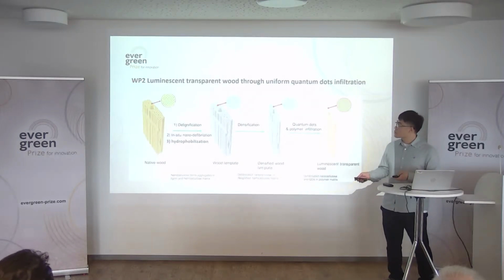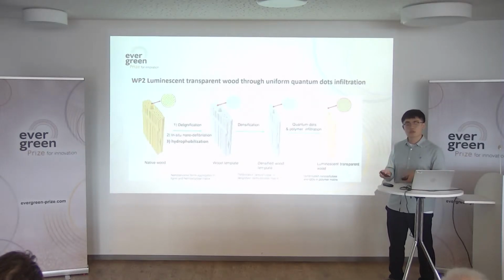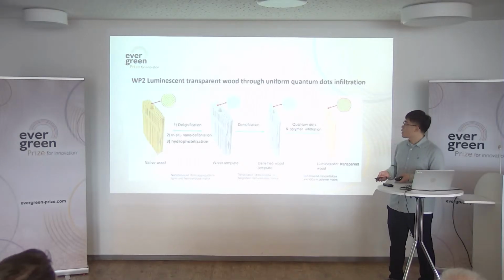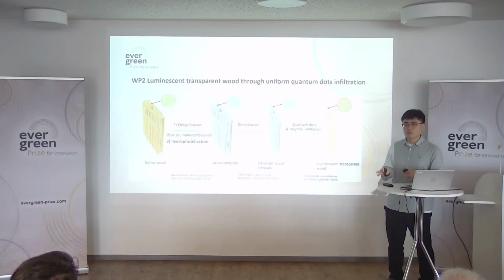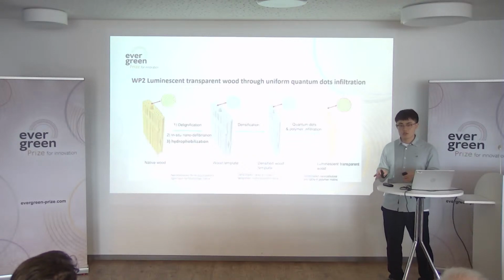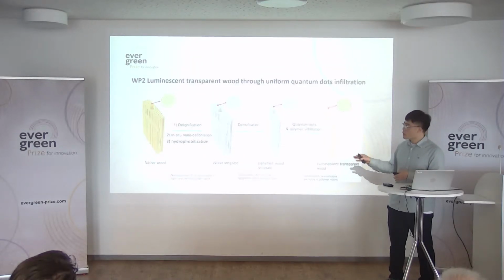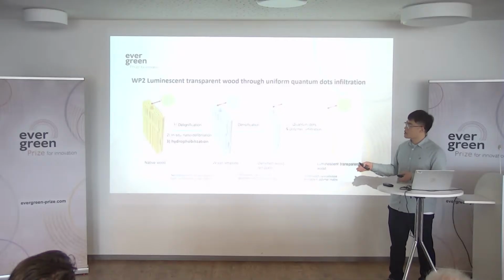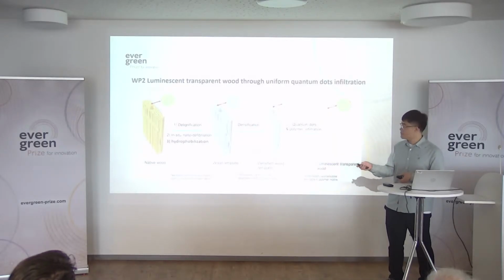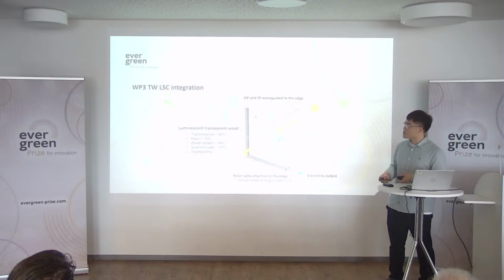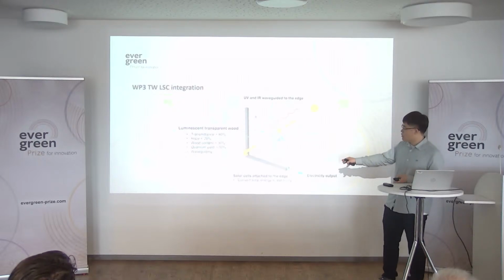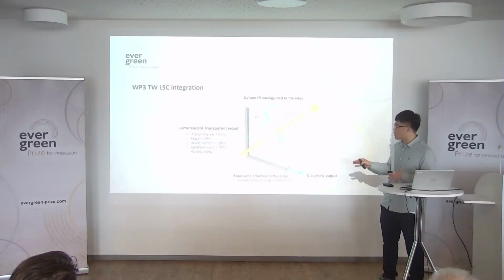The second step is to fabricate high quantum yield luminescent transparent wood. Normally the quantum dots are hydrophobic, and there will be heavy quantum dot aggregation inside the luminescent transparent wood. So we think the wood template should also be hydrophobized to improve the compatibility between the polymers, the quantum dots and also the wood template. After that, we do the densification and the polymer infiltration, and we can get a high performance luminescent transparent wood. And the third step is the device assembly. We attach the solar cell to the edges of the transparent wood, and it can convert the solar energy that has been wave-guided to the edges into electricity.